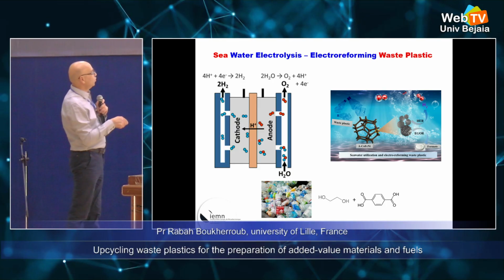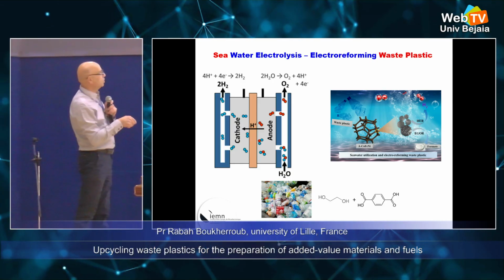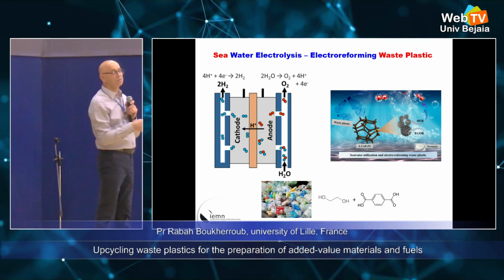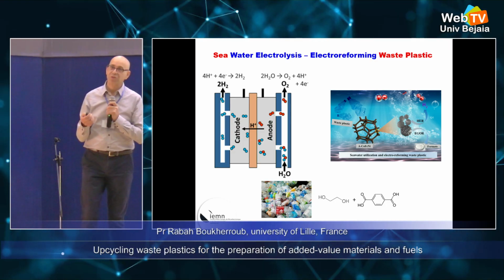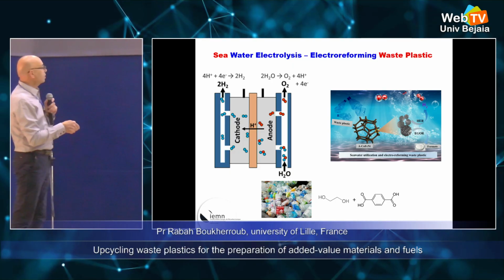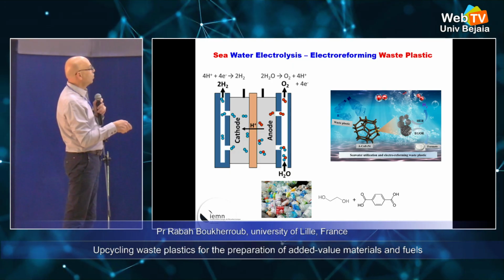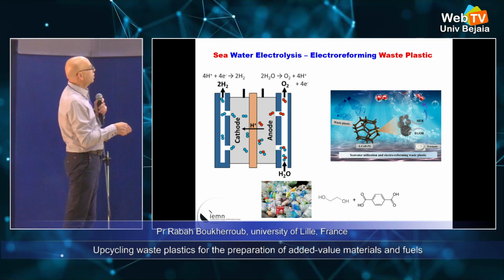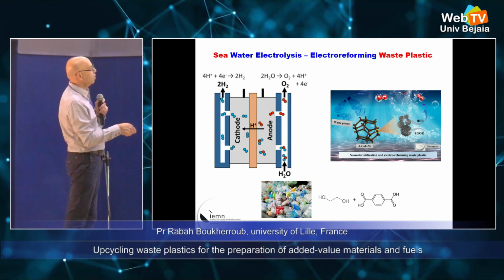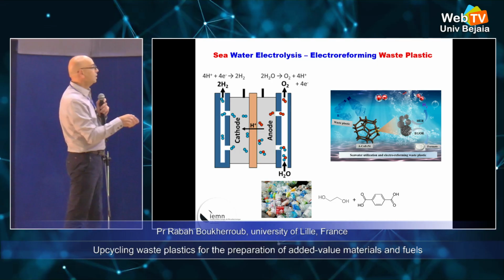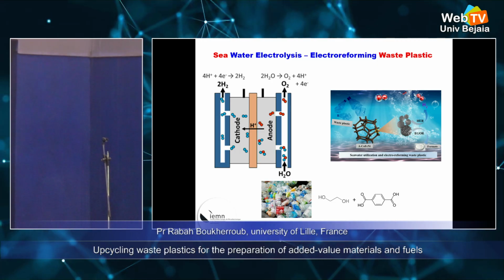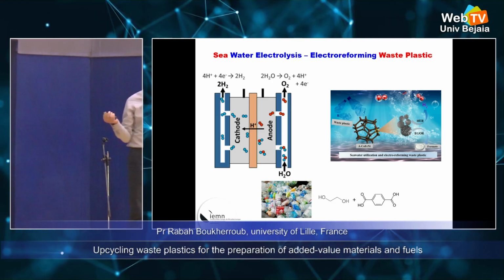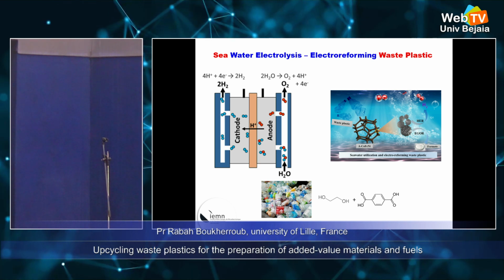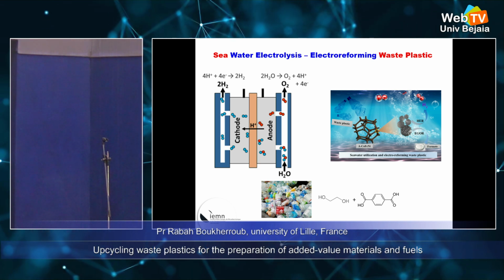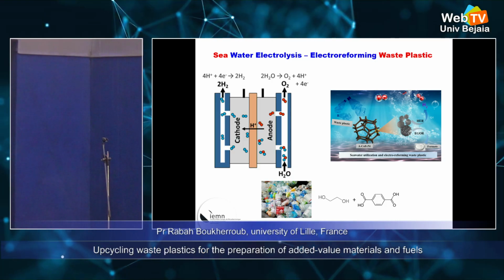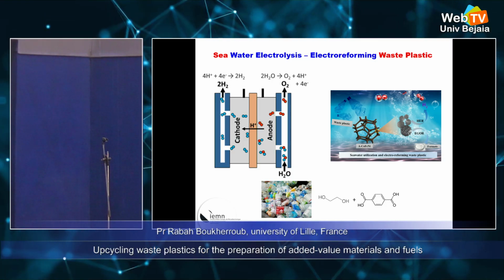So, if you work in electrocatalysis and water splitting, or hydrogen, if you want to generate hydrogen, what we do is you have a catalyst here and here, you have water, you apply a voltage, then you have hydrogen evolution at the cathode, and you have oxygen evolution at the anode. However, in this type of electrolyzer, and of course you have them at industrial scale to generate hydrogen, this oxygen is not useful. You do nothing with it. It's released.